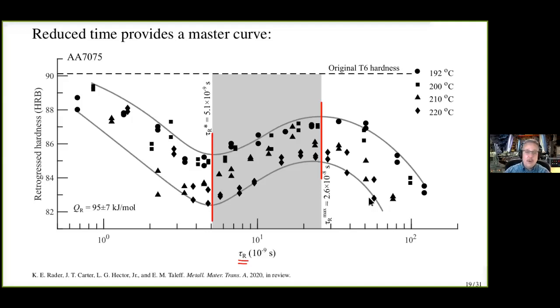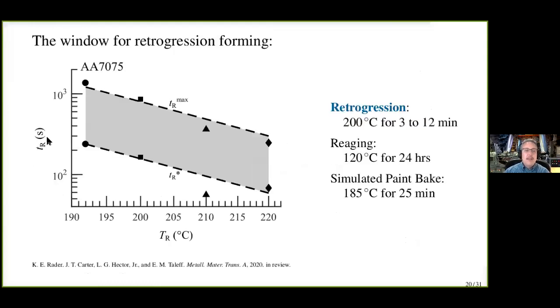Now that's very important because essentially all of our forming operations have to take place to the left of this tau R max value. So if we're going to form the parts, they have to be formed and then cooled down before we hit this value. So now we're able to predict process windows for our retrogression forming process. So we take that, and now let's take that predictive capability and plot a forming process window we can allow for 7075 T6. Okay, here we have it. This is our retrogression time, real time, not reduced time.